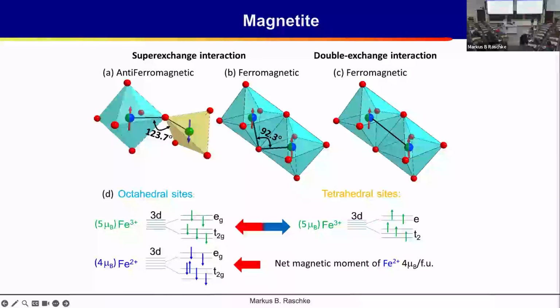So if you now look at these two ions here, we're zooming in on this octahedral site of one of the ions, and then the tetrahedral coordination where we have the 3+ cation, so this sits on that side. And through this interaction with this oxygen, these two irons interact, or their spins interact, through this oxygen ion. This is called the superexchange interaction. And in this case, this is the interaction when there is an iron 3+ sitting on this side. This is this scenario here. So we have a 3+ on the octahedral site and a 3+ on the tetrahedral site. And then they have the same number of spins of these electrons, and they can arrange in an antiferromagnetic order. And this is why those two completely cancel.